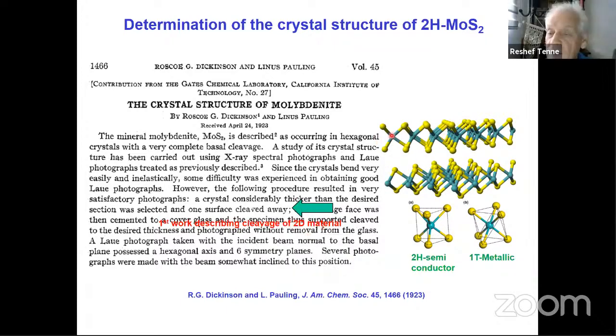So basically, the layers of molybdenum are sandwiched between two sulfur layers, and it's covalently bonded between the molybdenum and sulfur, yet between the layers there is only a van der Waals interaction, which is 50 times weaker than the covalent bonds, or even more.